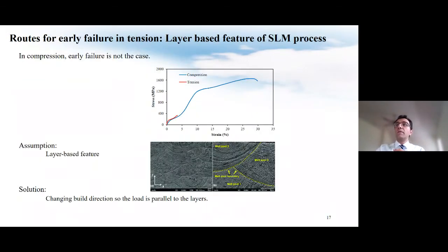While this set of process parameters result in perfect superelasticity, both in tension and compression, we figured that the tensile strength of all specimens was significantly lower than the compressive strength, as you can see here. I should mention that this major drawback is not only associated with the SLM fabricated nitinol, but also observed in all fabricated specimens with different materials. Therefore, we started to identify the roots for early failure in tensile testing specifically, and provide some solution to address this issue. Our first hypothesis was that the layer-based feature of SLM specimens results in such an early failure.